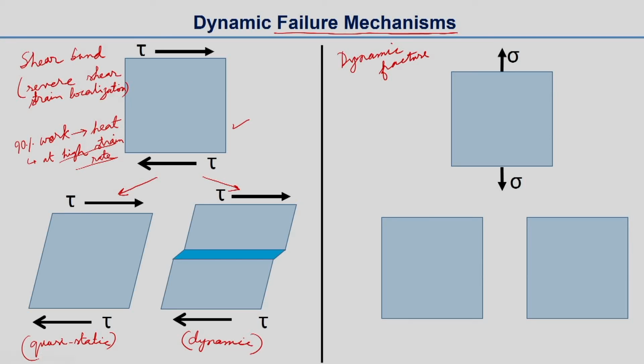So, most of the work spent in plastic deformation is converted to heat, and due to that heat, a high temperature is generated in some local area, and because of that the material softens in that part. Due to the high rate of loading there is not much time to diffuse the heat away from this area. So basically this part would be softened due to high temperatures, and it will have severe shear strain localization.